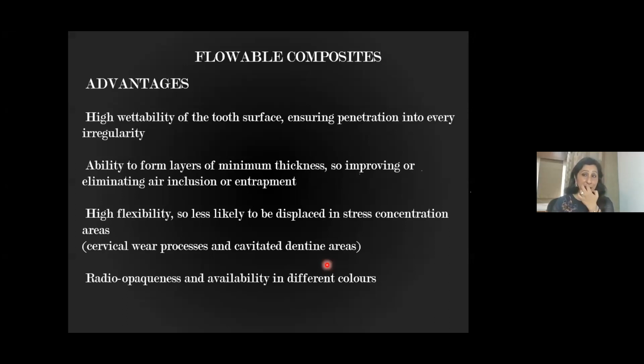But with this flow, which I'm going to talk about, you hardly can entrap any air bubbles in them. So flowable also has very high flexibility, so less likely to be displaced in stress concentration areas. So wherever there is stress concentration areas and where you need flexibility, that is of course in the cervical abrasions, when you do class 5 restorations, the liner or base should be with flowables to give you the best flexibility as well as the best placement of the composite over it so that they can serve you for a very good time. The longevity of the restoration increases.